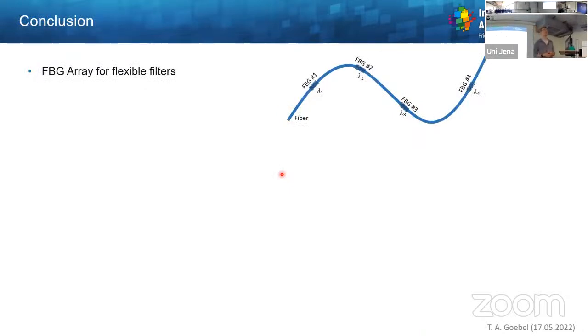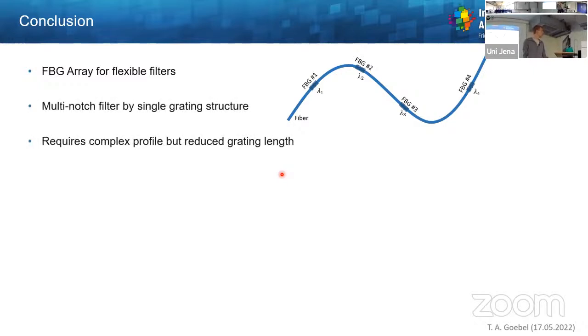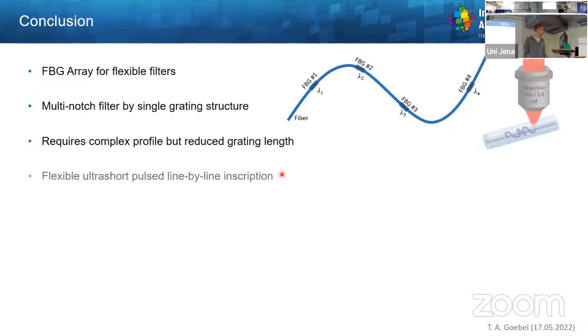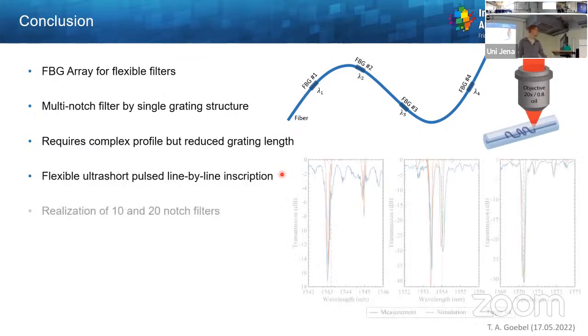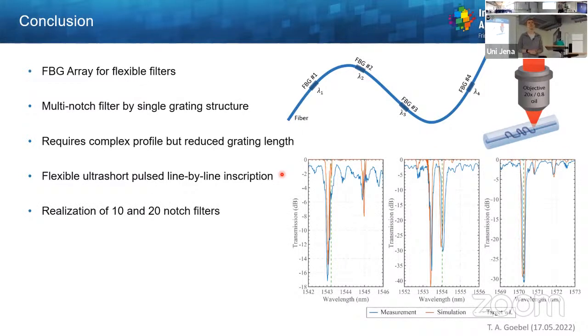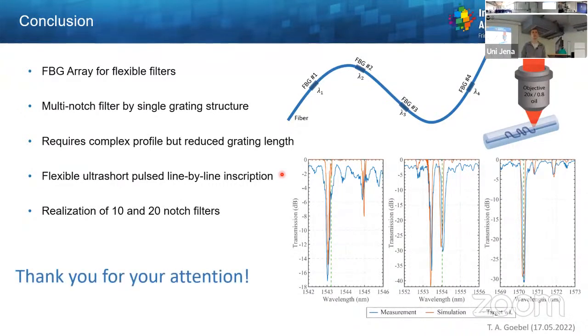So basically, for achieving multi-notch filters, we can have either an array of fiber Bragg gratings written right after each other into our fiber. This is a very stable and reproducible process, but comes with the expense of having large areas of structured fiber, which might need to be stabilized if you are working in a non-stable environment. This can be overcome by inscribing complex grating structures with the line-by-line technique, which is a very flexible tool to address these structures. And with this, we could inscribe resonances with 10 and 20 notches. And with this, I'd like to thank you for your attention and welcome your questions.